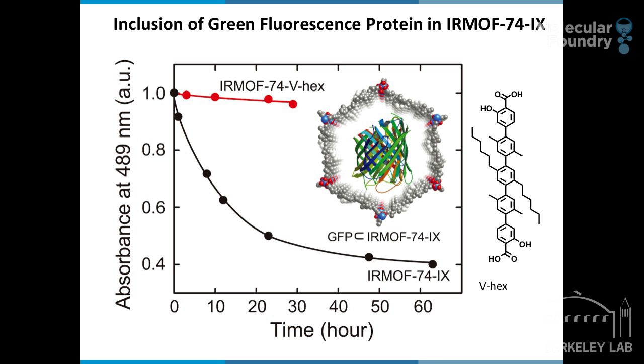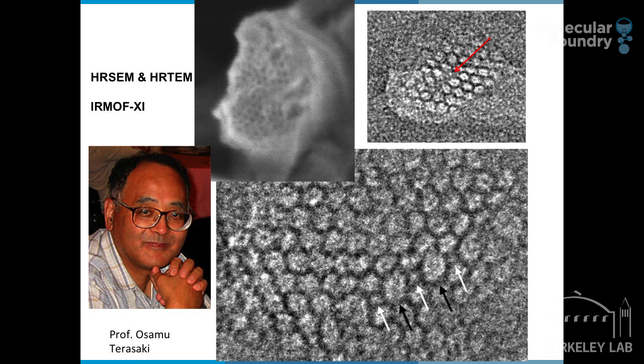We are still examining the chemistry of the largest members of this group. Another really major achievement here is that MOFs have always shown electron beam sensitivity. And so through my collaboration with Professor Osamu Terasaki, he has succeeded in observing through SEM and TEM the pores of MOFs. This is giving us a lot of ideas on the chemistry that happens around the opening of the pores. So where is MOF chemistry going?